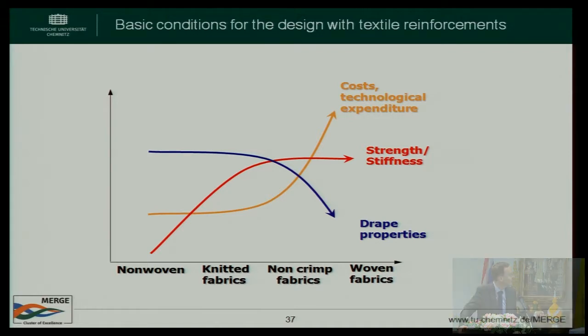So, looking at the summary of non-woven, knitted fabrics, non-crimp and woven fabrics: the stiffness and strength we reach already with non-crimp fabrics are at a really good level, but the drape properties are much better compared to woven, and the cost and technological expenditure is much higher for woven. Non-crimp fabrics start already compared to non-woven. Non-woven is easy to make, but the fiber volume content and the fiber orientation are not such that they reach a good strength and stiffness.